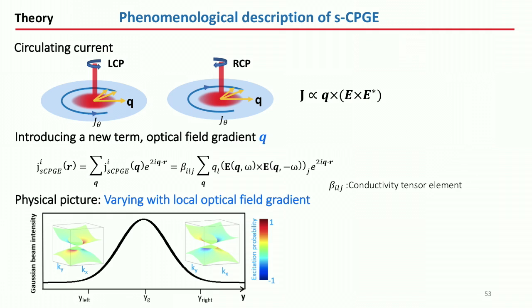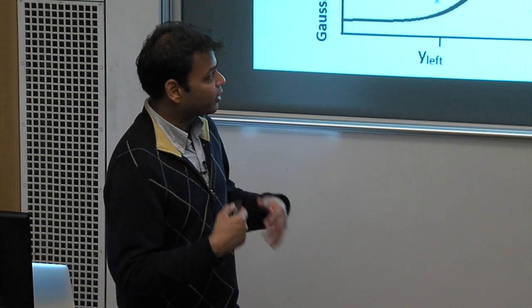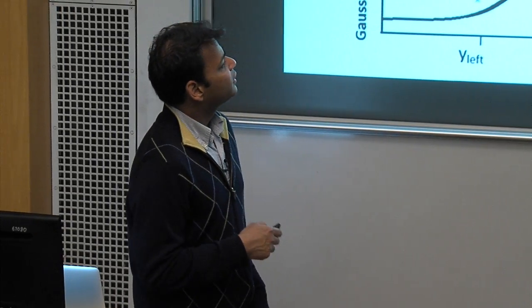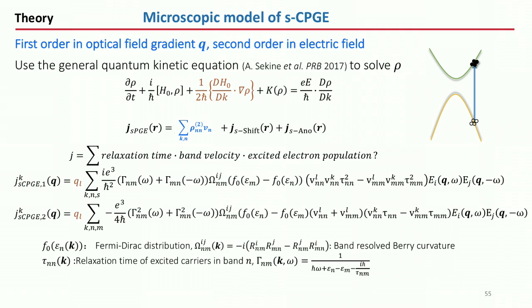But the interesting, unique aspect here is that the response is non-zero only if, in K space, the excitation at K and minus K is different. So this means inhomogeneous excitation of carriers in K space. So the plus K value and minus K value have to have different excitations. Okay, and then she derived the new response functions. The important thing is that these response functions include this in-plane momentum.